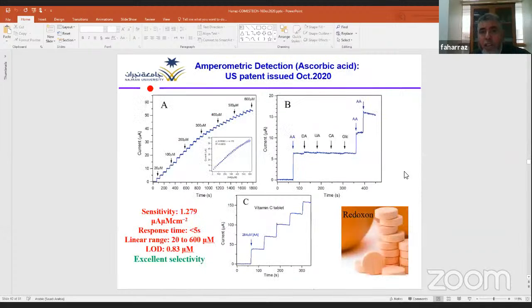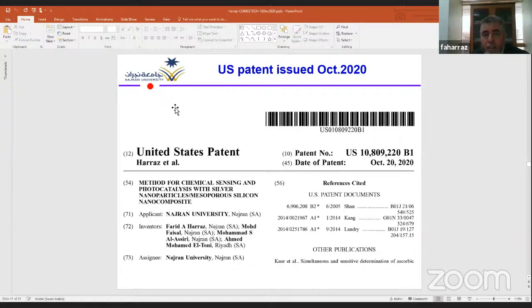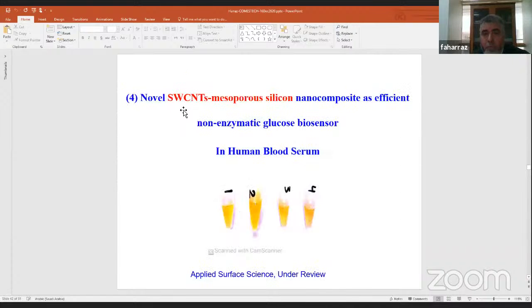And this is the amperometric detection of ascorbic acid. This is a very interesting result we have obtained. The sensitivity of this sensor is very good, with a response time of less than 5 seconds and a wide linear range from 20 micromolar up to 600 micromolar. And the limit of detection of our sensor device is very low, with excellent selectivity. In addition, we have validated the performance of our sensor device using some vitamin C tablets. For this work, we filed a US patent, and it was officially issued in October 2020.